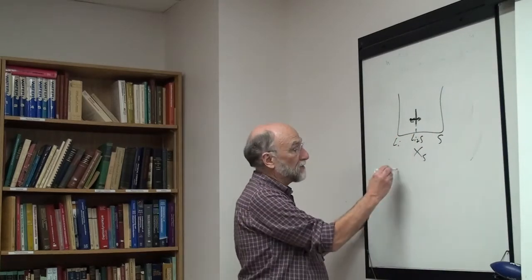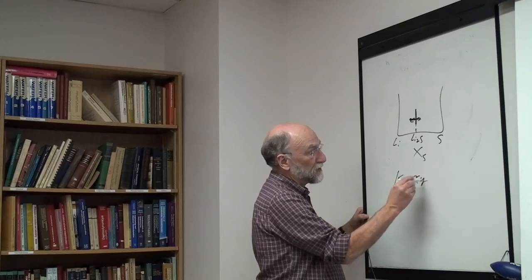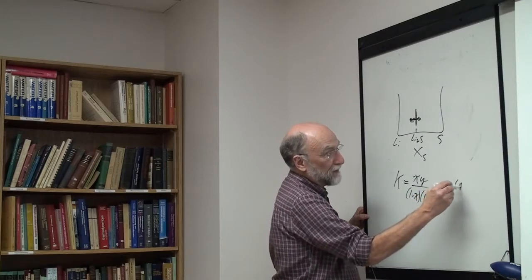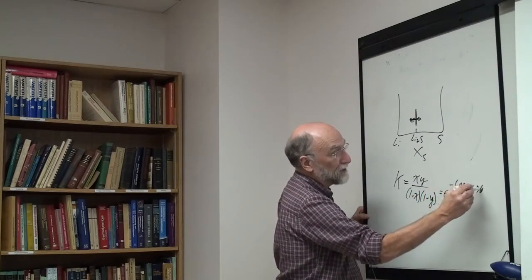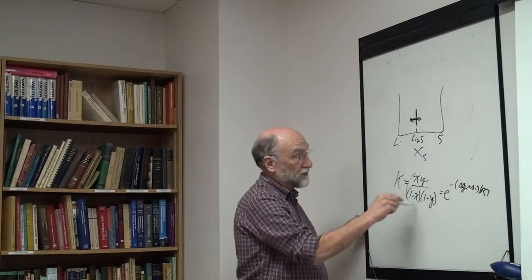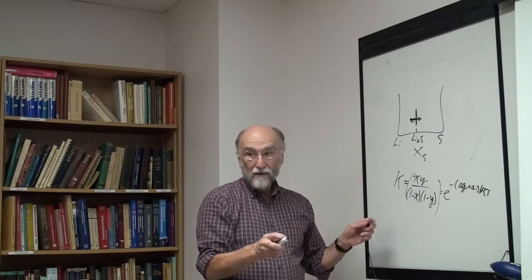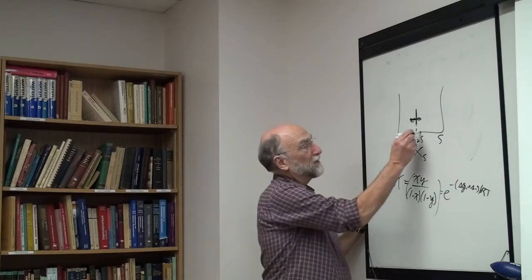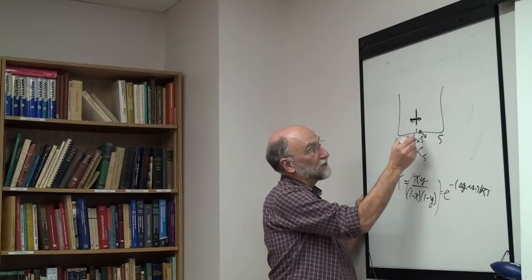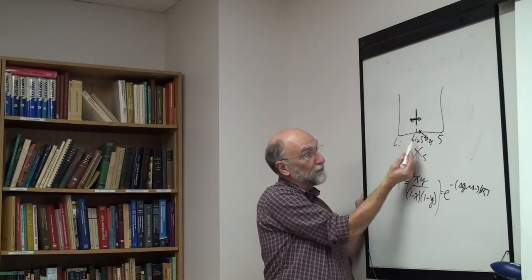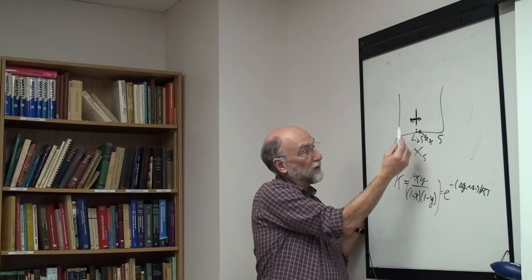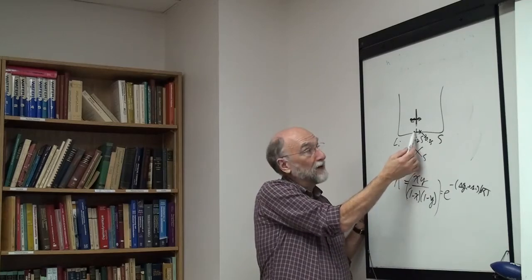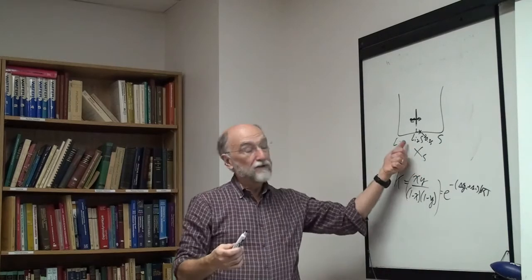So you're going to have an equilibrium. Remember, we ended up with an equilibrium constant: K equals x y over 1 minus x times 1 minus y equals the exponent of minus delta G1 plus delta G2 over RT. Okay? So you solve this equilibrium constant for x and y, and you have a mass balance. You give your total lithium content. If your total lithium content is, say, 0.35, which means you're a little bit away from the 33%, then you can work out the total amount of lithium.